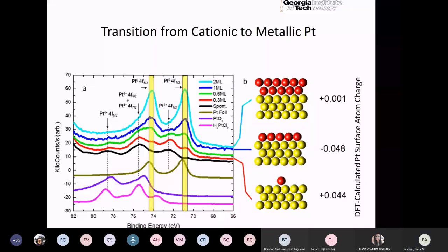So here we're looking at, if you look at this legend here, the samples that we're studying are 0.3 ML, ML stands for monolayer, 0.3 monolayer, 0.6 monolayer, 1 monolayer, and 2 monolayers. And so that would be these here. And we also have one that's called spont, that's for spontaneous. The spontaneous means that we just dip our substrate into platinum solution, and we just pick up whatever platinum comes onto the substrate without an electrochemical reaction. That is, we're not reducing the platinum electrochemically, we just pick it up. Compared to these 0.3, 0.6, 1, and 2, those are done through this SLRR or electrochemical reaction.